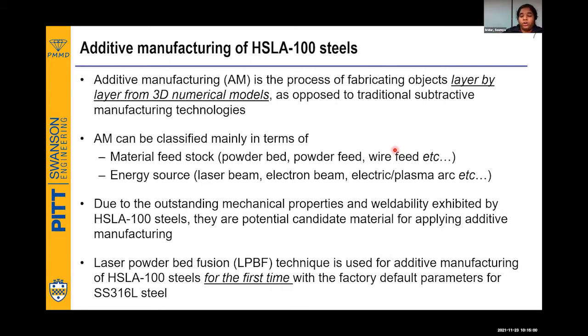Like, I also work on wire feed additive manufacturing, and we have built a tube which is almost, I would say, 150 to 200 centimeter long, which is not possible using a powder bed process. And secondly, the energy source. So mostly the most common is laser beam. Typically, most of the materials can be processed using laser beam, and some of the materials using electron beam.